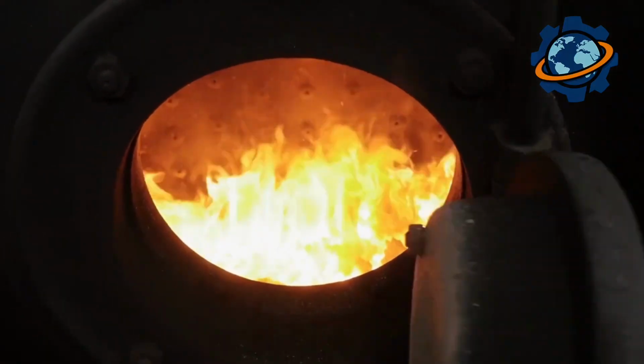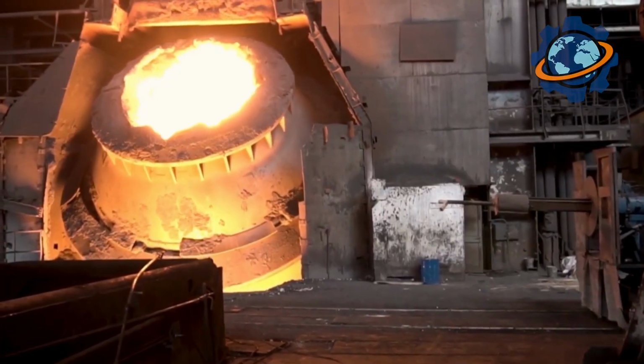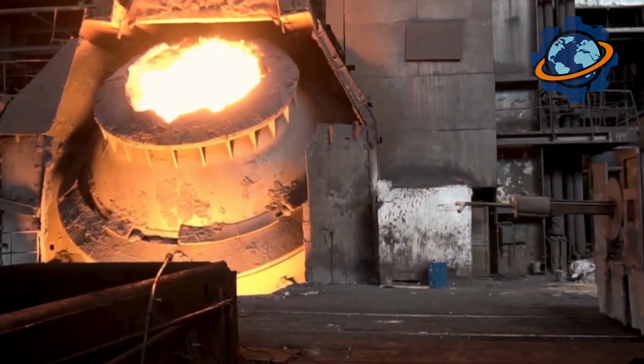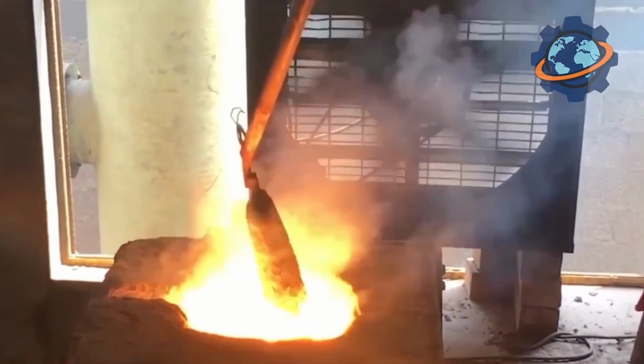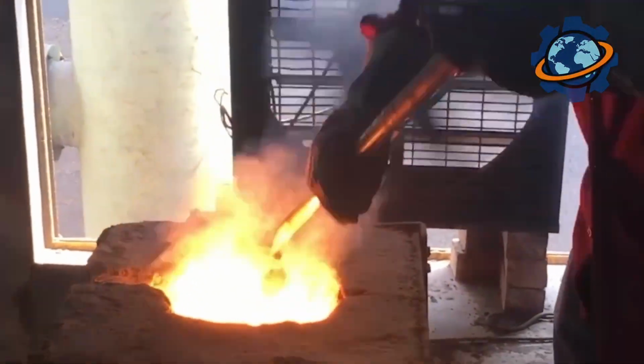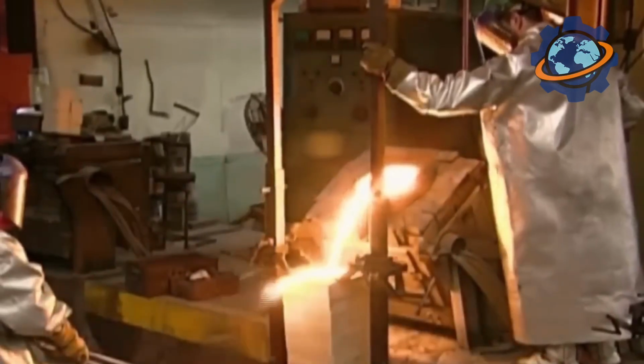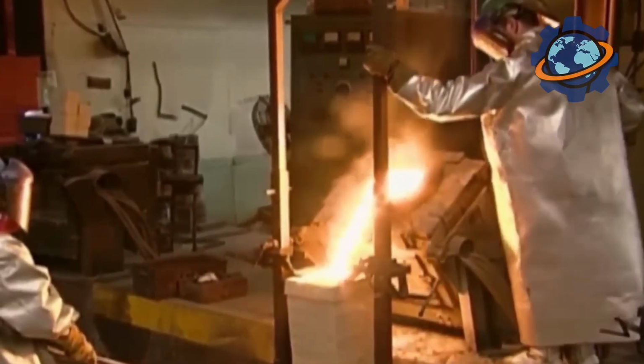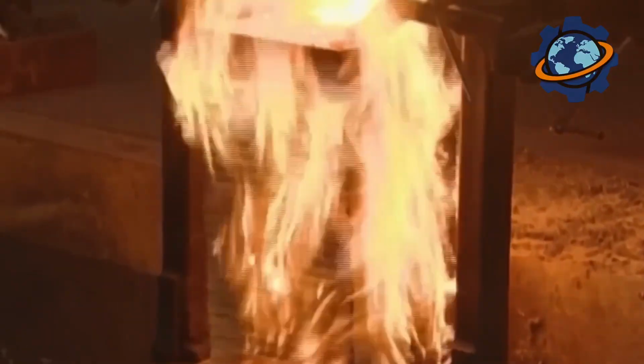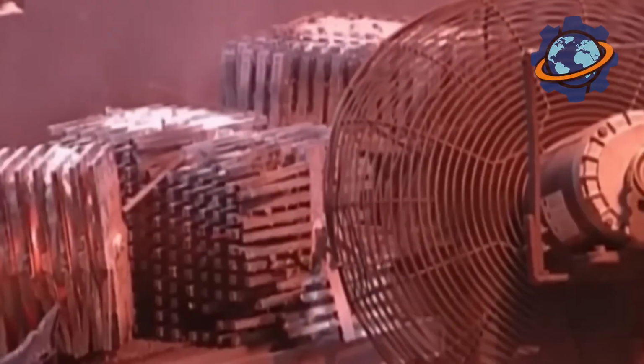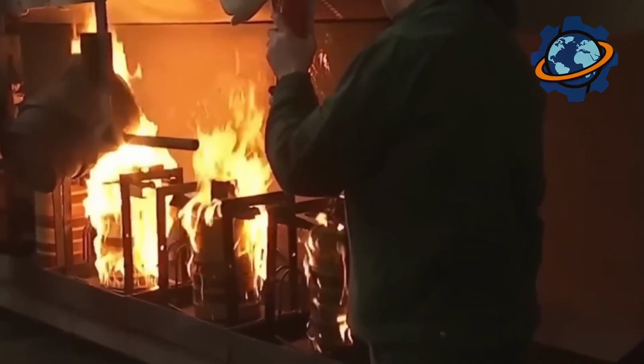After achieving a complete melt and homogenization of the alloy, the stage of rapid cooling, known as the strip casting method, begins. This is a key moment for forming the optimal microstructure. The molten metal is poured in a thin stream onto a rapidly rotating, cooled drum. Contact with the cold surface of the drum leads to an extremely rapid cooling of the melt at a rate of up to millions of degrees per second.